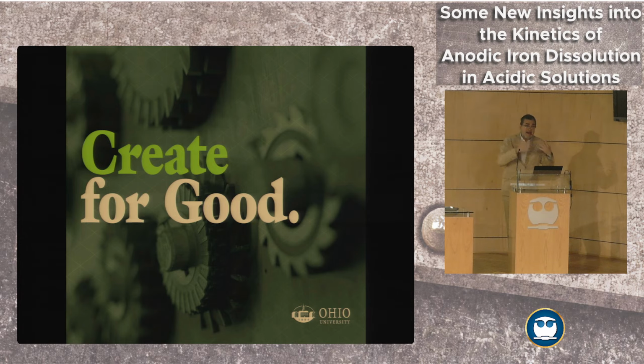So in a way, iron, which is a very reactive metal, will always corrode, it will always dissolve, but it needs help. It doesn't just leave the iron lattice and go into solution. It needs help from chlorides or hydroxide or both in order to do that. So aqueous environments that have chlorides or hydroxides or both are not good for iron. Iron will dissolve faster than without them. Of course, it will dissolve even without chlorides and without hydroxide, but not as fast. It will take much longer, so these two are bad guys.